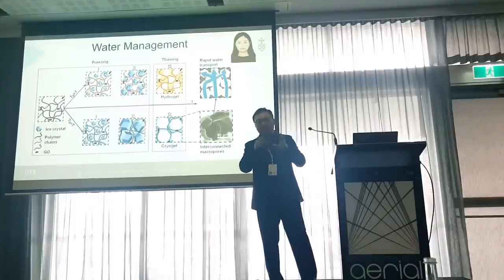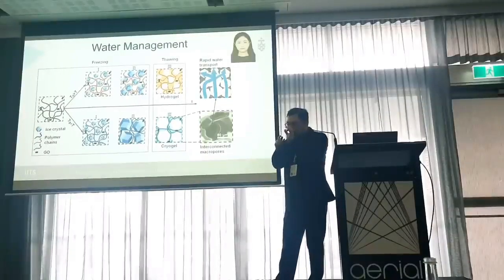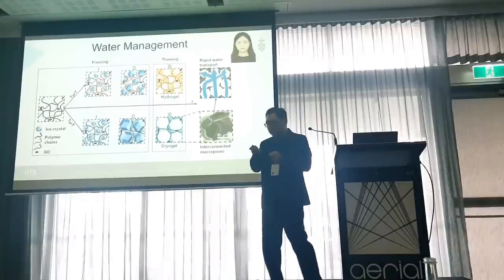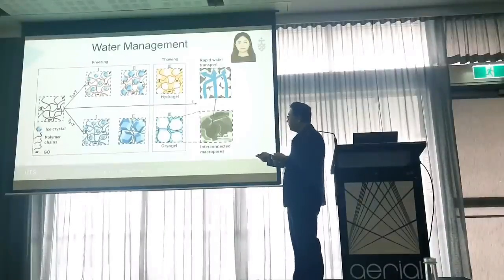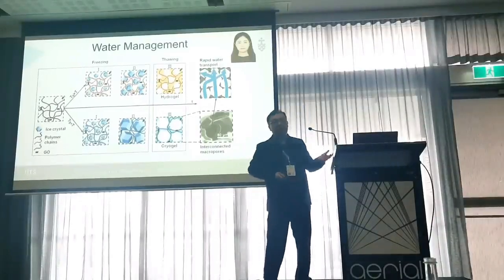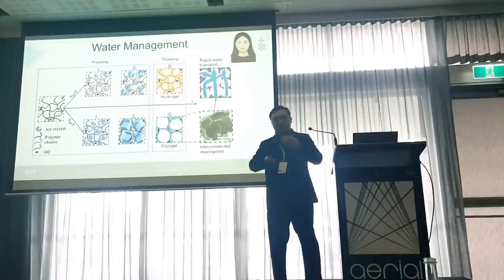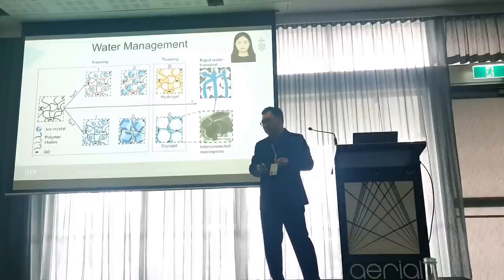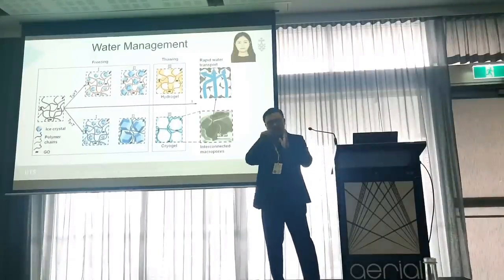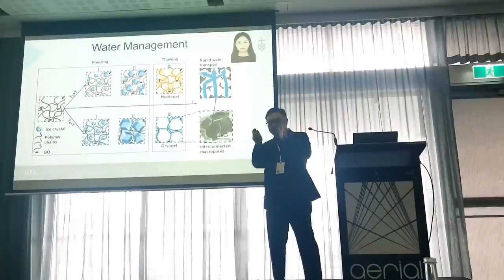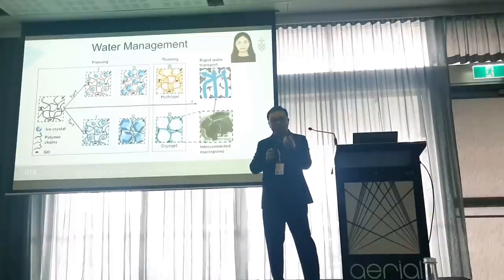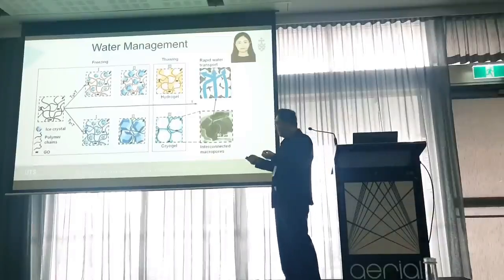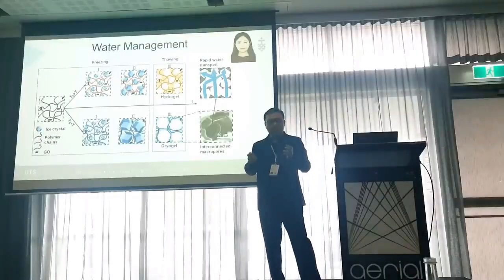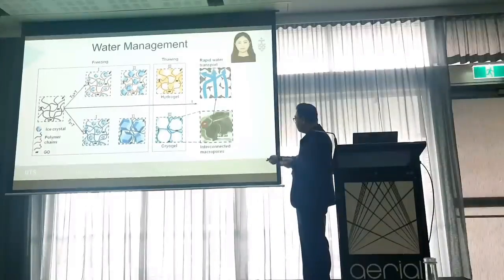So finally, we obtained a micropore structure with a lot of small pores. That's the case of PVA hydrogels. However, in the case of PEG hydrogels, the Tg of them is very low, below minus 40 degrees Celsius. Therefore, during the freezing process at minus 18 degrees Celsius, the polymer chain still shows high mobility. So the water crystal in this hydrogel can grow larger and larger, not limited by the polymer chain. Therefore, finally, we will obtain a very large pore size, yeah?